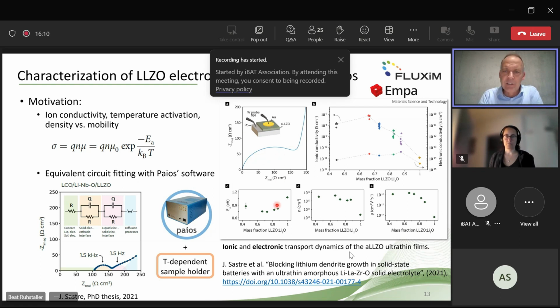And for a variation of the temperature, it was possible to determine the activation energy, which is simply defined here in this equation. So the conductivity is split into a density of carriers and the mobility, and also the temperature dependence is there. And there are further methods that allow you to determine not only the ionic conductivity, but also the electronic conductivity.